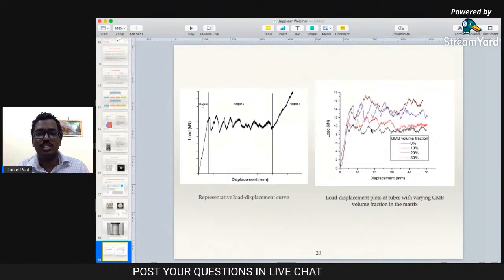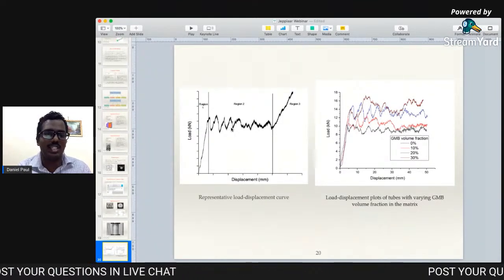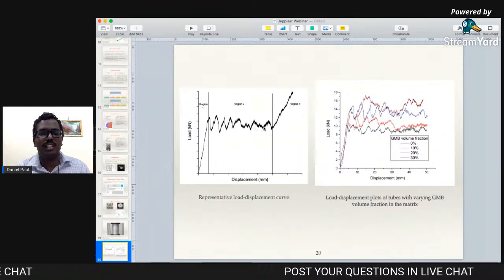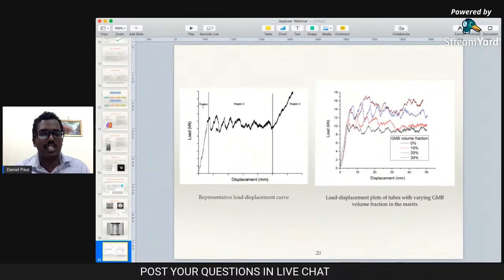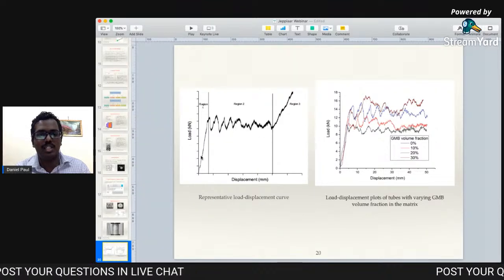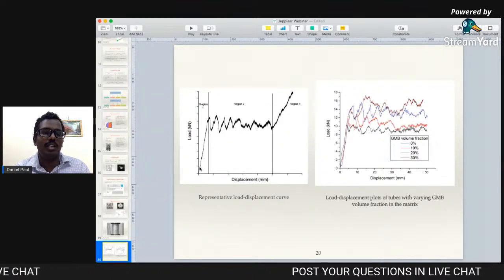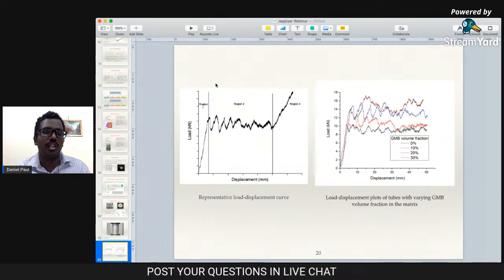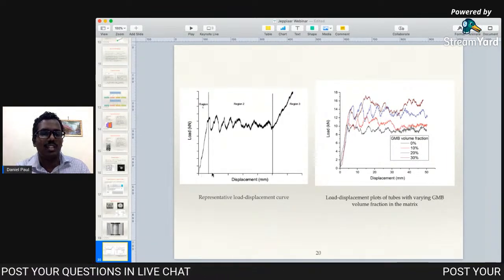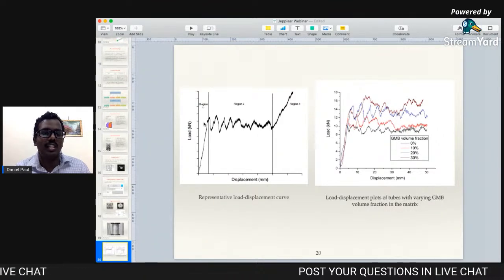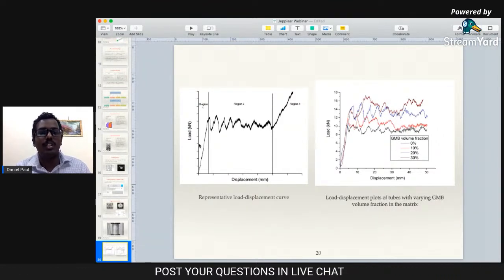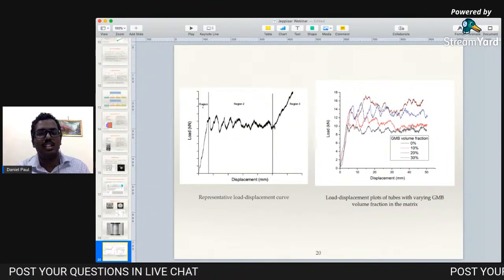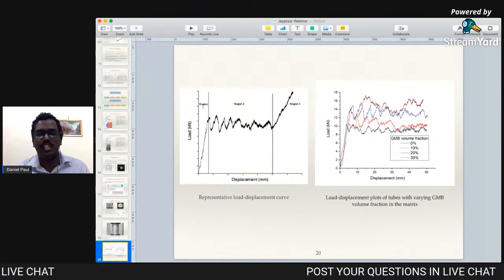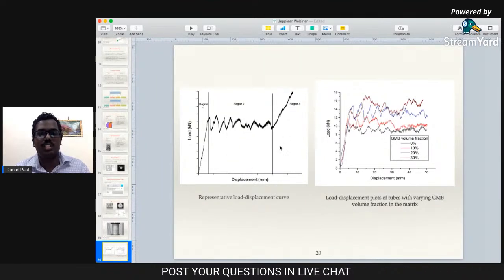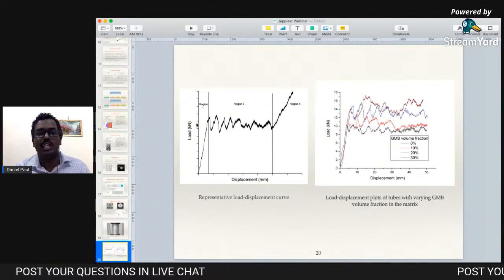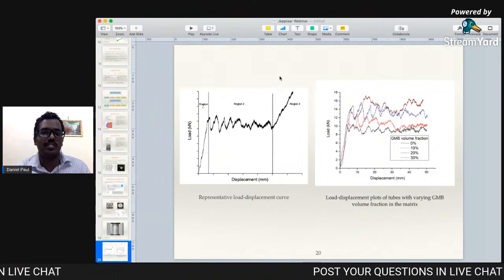Also, an important point here is that the energy absorbed by the material or the structure is given as the area underneath this load displacement plot. So if you just have a material which withstands a very high load and then breaks suddenly at a very low displacement or deformation, the area under the curve is going to be very low. But on the other hand, if you extend the area under the load displacement plot like this, you get a very high energy absorption. So this is the difference between catastrophic failure and progressively damaged failure.